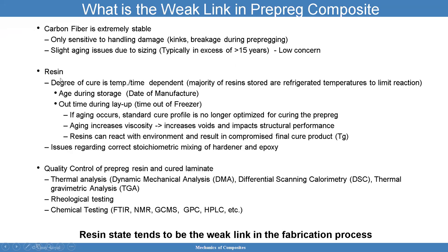Resin, the degree of cure is temperature and time dependent. We cover that a lot. Majority of the resin is stored at cold temperatures to limit the reaction. You have aging during storage. So we talked about that, the date of the manufacturer. Out time, how long it can be out of the freezer, we talked about that. If aging occurs, the standard cure profile may not be optimized already, may not be the right one. So you have to kind of study that too. So we call those aging studies.